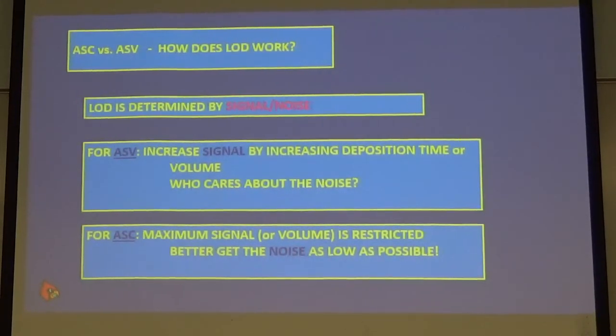The problem with that is that you double the volume, you're increasing the thickness of the cell, which means you have to wait longer to deposit, to exhaust the entire cell. And it's a losing game. You double the thickness, that doubles the signal, but it increases the diffusion time by 4. So there's a limit to how much you can get by going that direction.